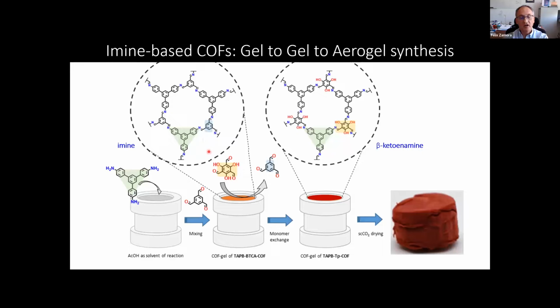Then in a second step, once you have the gel formed, you can do a monomer exchange reaction in the gel form, substitute one of the components, and then arrive at a new structure. So you pass from imine to ketoenamine, for instance. And once you have the gel, you can apply a solvent exchange and supercritical CO2 drying, and then you can form the monolith of the COF aerogel. So you can do something else.